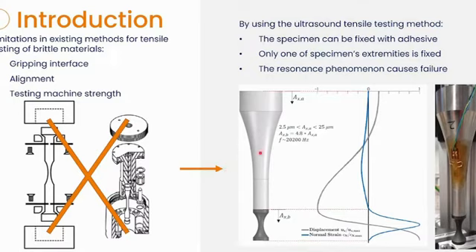So in the ultrasound tensile testing method, the same machine used in the very high cycle fatigue tests is adopted. But in this case, we aim to cause the failure of the specimen in as few cycles as possible, so as to avoid fatigue fracture.